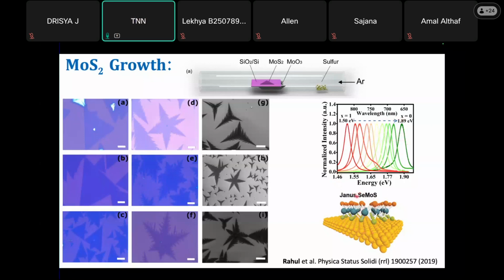You can also create Janus structures. We have recently been quite successful in making such Janus structures. What is Janus? Janus TMDs are two-headed systems. That means the top layer is selenium and the bottom layer is sulfur, or the other way around. In typical molybdenum disulfide or selenide, both layers are sulfide or both are selenide. But here, one layer is completely converted to sulfide and the other layer is completely converted to selenide. Such structures have quite interesting properties, because an induced dipole moment automatically comes into the picture, since sulfur and selenium have different electronegativities. This creates a lot of interesting things, both electronically and electrochemically. I'm not going into the details of that, but you can have such control over it.